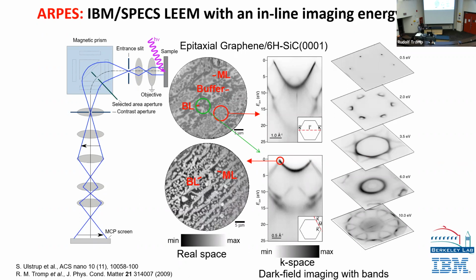Now we can place a small contrast aperture just on the Dirac point, just at the singularity at the edge of the Brillouin zone, and form an electron image with just these electrons. Right? So now we select a tiny spot out of the total 3-dimensional band structure out of this material and form an image just with those electrons. So you can see there's bright areas and dark areas. The bright areas carry these electrons. That's where we have graphene. Where we have these dark areas, we have no graphene. So it allows us to study the band structure in detail, but then we can carry that back to the image and see which pieces of this band structure appear on the sample, right?